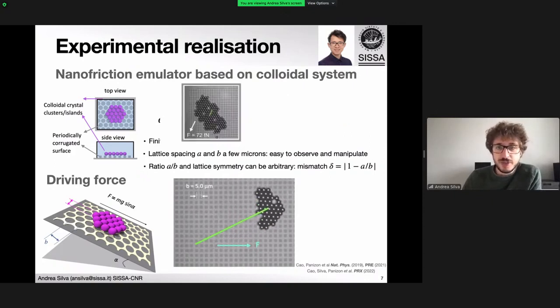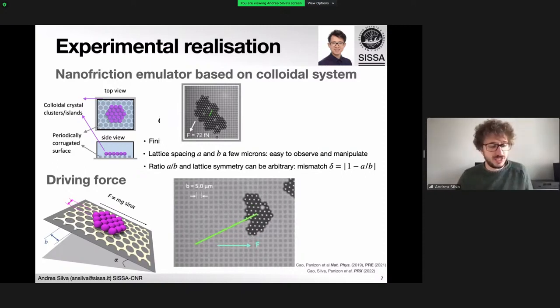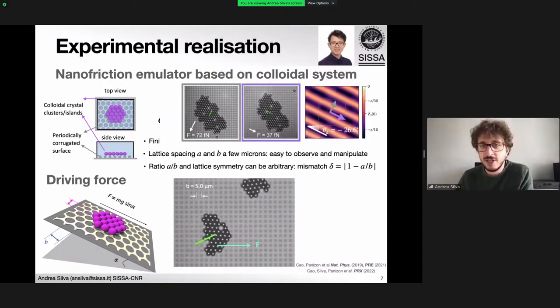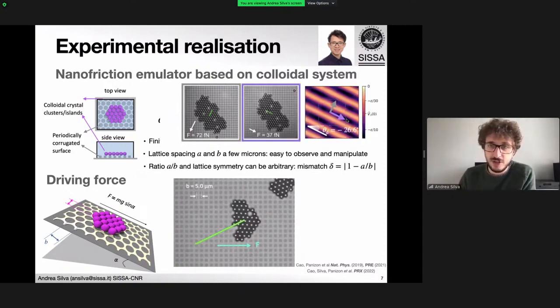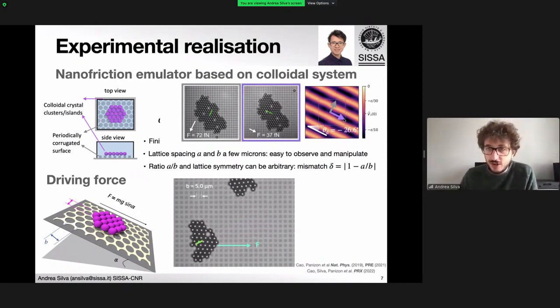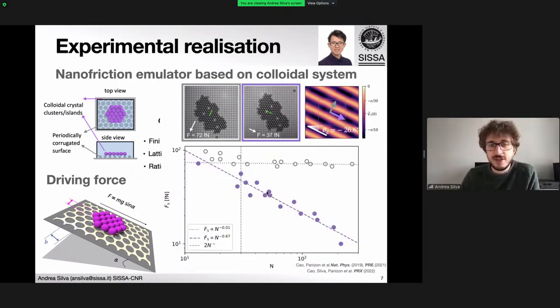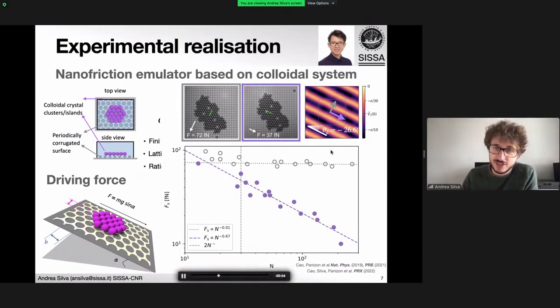And if we probe the system along two directions, where we create a system that should exhibit directional superlubricity, as predicted by the theoretical model, we see that the friction along the valley and perpendicular to it nicely falls in between the predictions of the theory. So we are constant when we go across the ridges, and it scales sublinearly with size as we go along the valley.